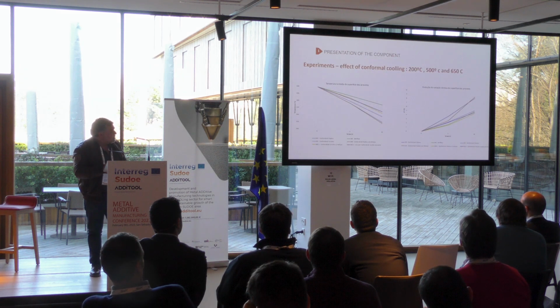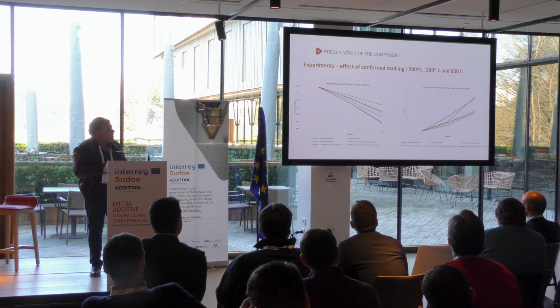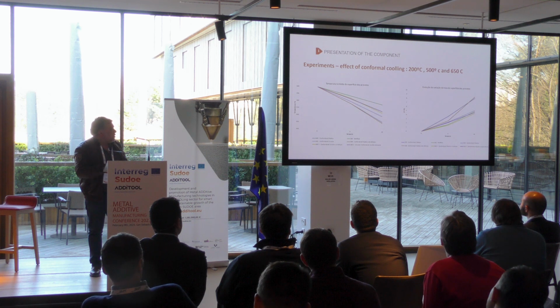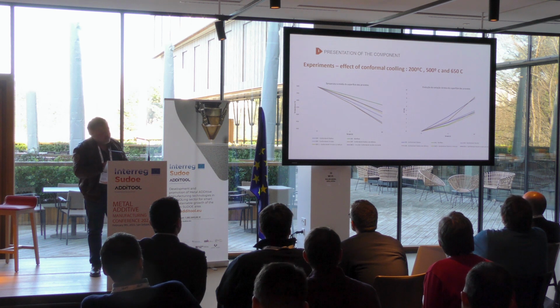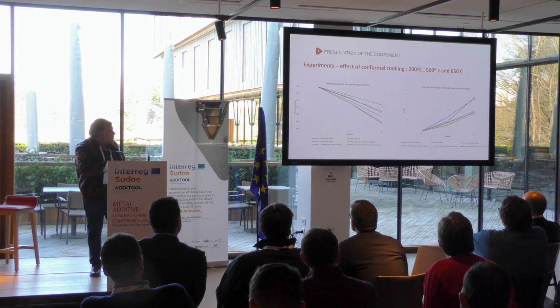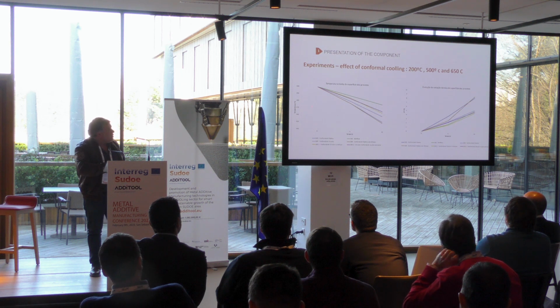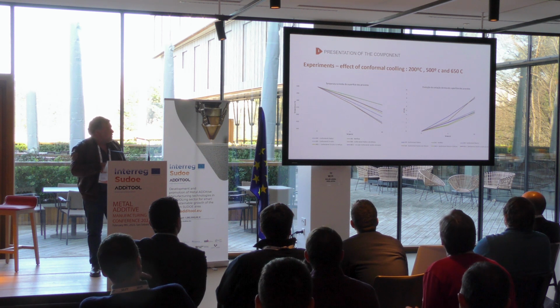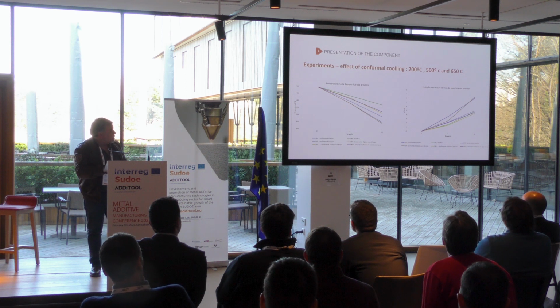These are only some tests, but starting from 200, 500, and 650 degrees, we have a reduction of more or less—if you take a straight vertical line, the green is the vertiflow, and the others are the conformal designs with elliptical shapes, with fins and without fins—we achieve a 10% reduction in cooling time.